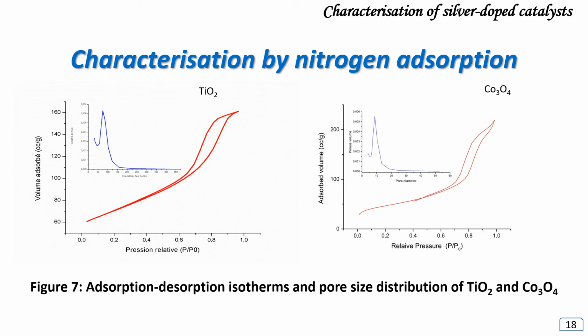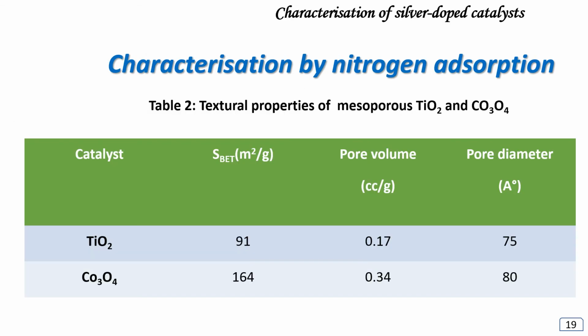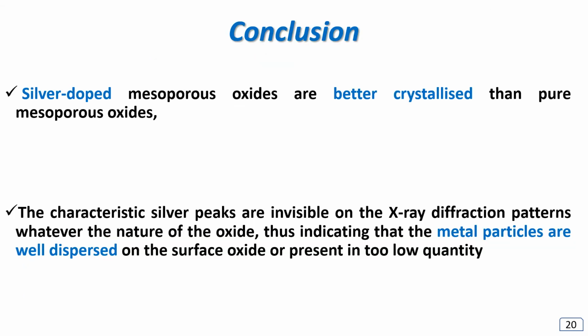The figure shows the adsorption-desorption isotherms and pore size distribution of titania and cobalt. The table shows the textural properties of mesoporous titania and Co3O4. In conclusion, silver-doped mesoporous oxides are better crystallized than pure mesoporous oxides.